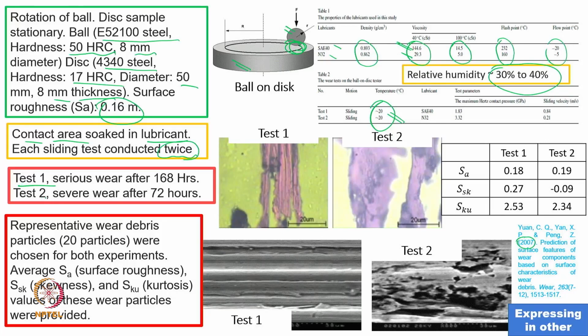Now, what they mention: test 1 is with lubricant 1 and test 2 is with lubricant 2. In this case they experimented, and because of the high viscosity they found that severe wear occurs only after 168 hours, while in the thinner oil N32 the severe wear occurs after 72 hours. That is what they have done.